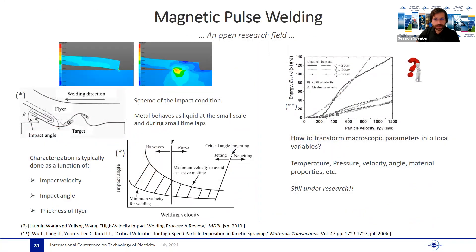As I mentioned at the beginning, one of the most interesting cases is welding applications. When dealing with impact welding, today most of the experimental works focus on determining what are called welding windows, which enable defining whether the surface are welded or not, as a function of the relative velocity just before impact and also the angle between both surfaces. It is an open research field, and one of the key questions is how do these process variables, the velocity and the impact angle, transform into the thermodynamical variables, temperature and pressure, and then also to develop empirical models that can quantify not only weldability as a binary state, but also the quality of the weld as a function of the thermodynamic history and the material properties modification.